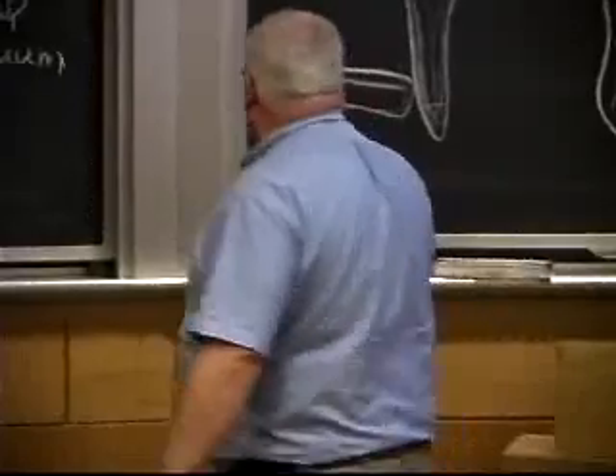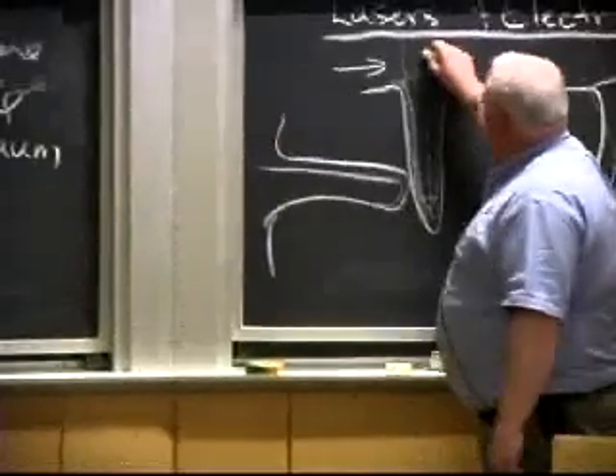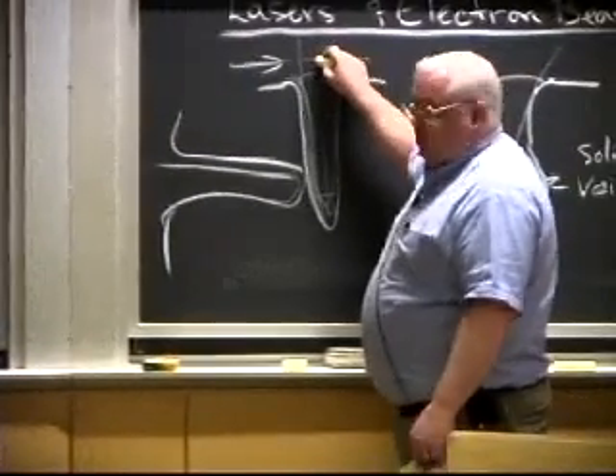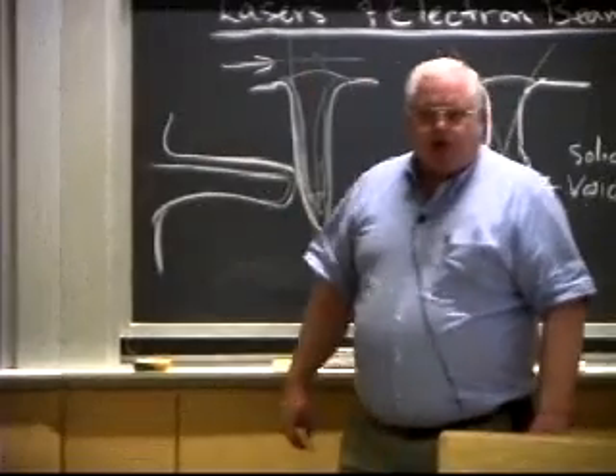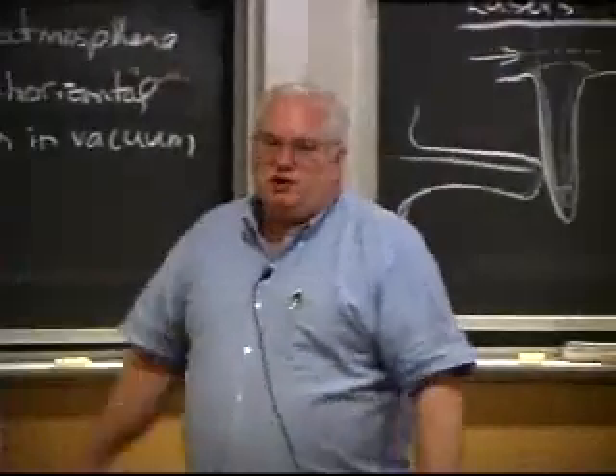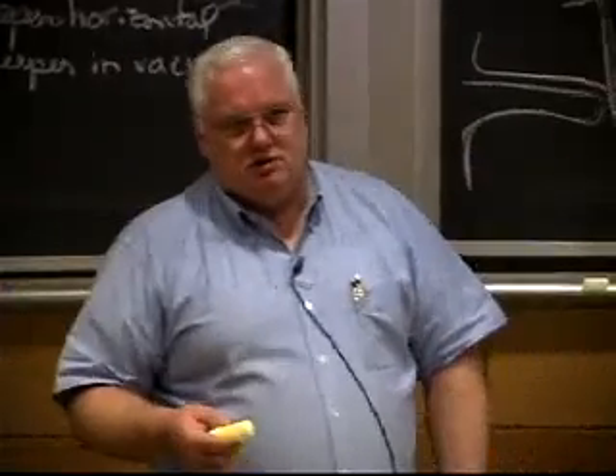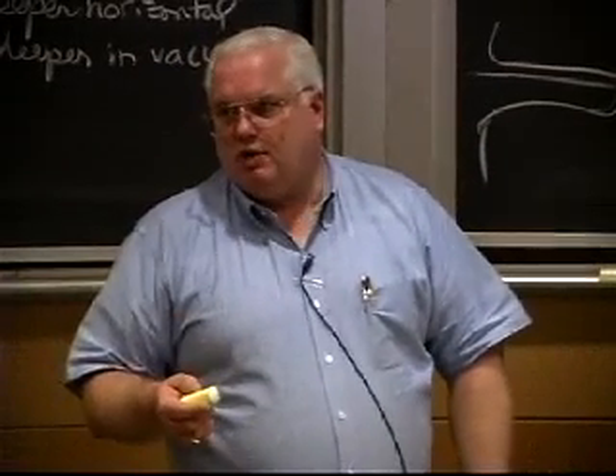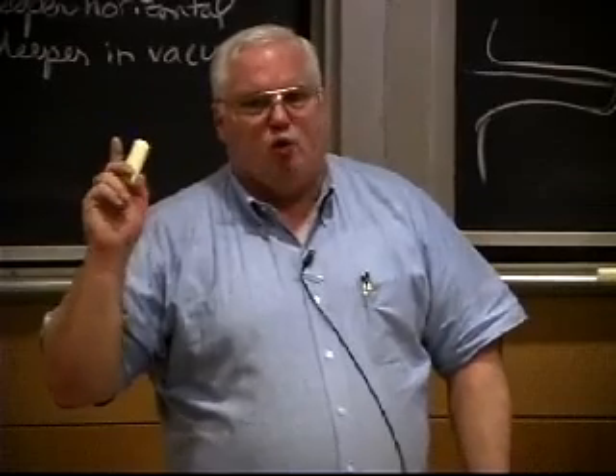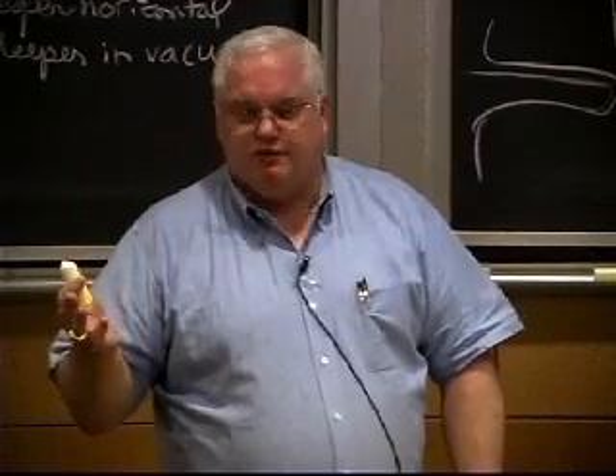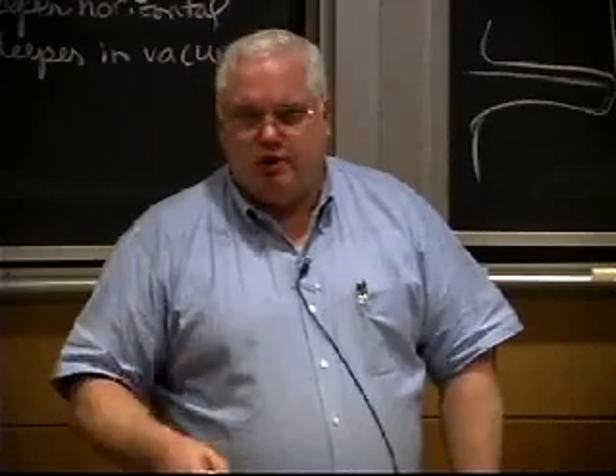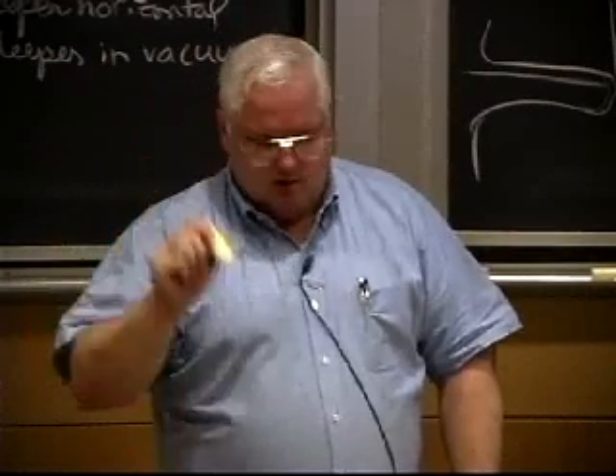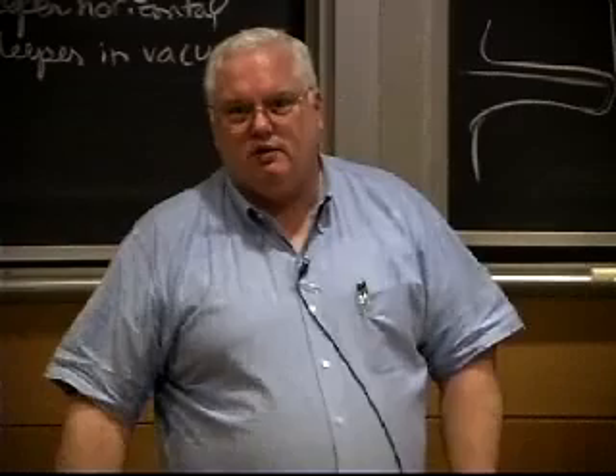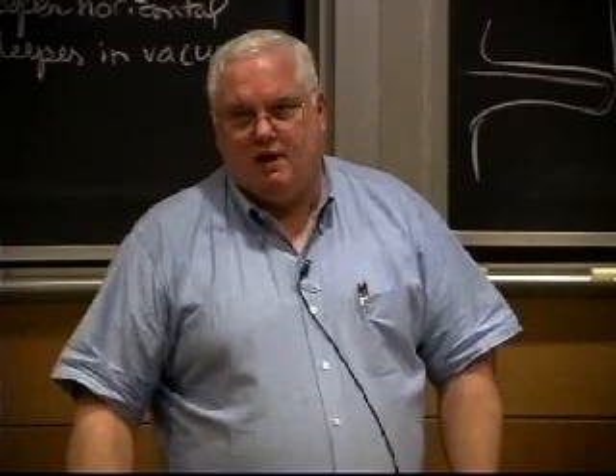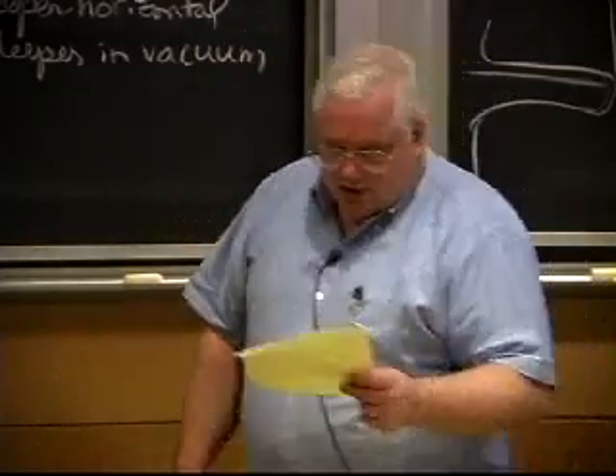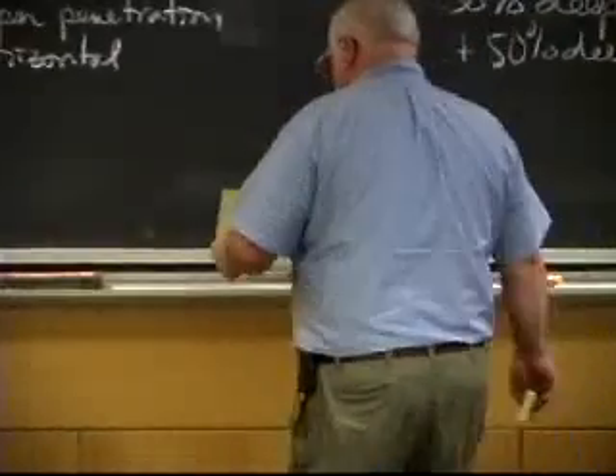And the reason is the same thing I talked about before. If you get this metal vapor coming up here and air up here, that will partially block the beam. It turns out you can get significantly deeper penetration for the same powers in electron beam than you can laser, because the low energy photons are more easily blocked by the gas vapor on the surface than the high energy electron beams. These 100,000 volt electron beams will just blast right through this layer of vapor on the top surface that's coming off, okay? But the laser photons don't do nearly as well, okay?